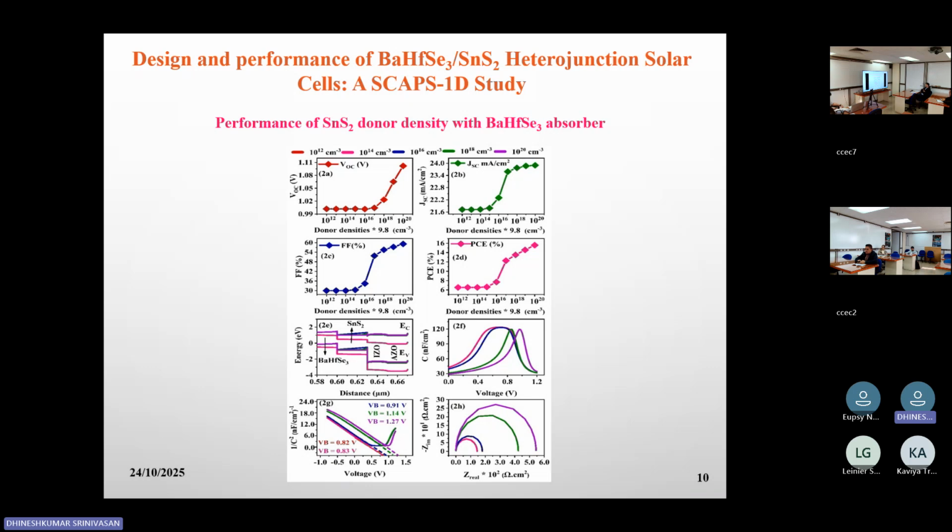The electron barriers at the absorber buffer interface and the buffer IZO interface also stay high. In contrast, when the donor density exceeds the absorber acceptor level, both the conduction band and valence band in the buffer shift upward, lowering the interfacial barrier and aiding the charge transport.